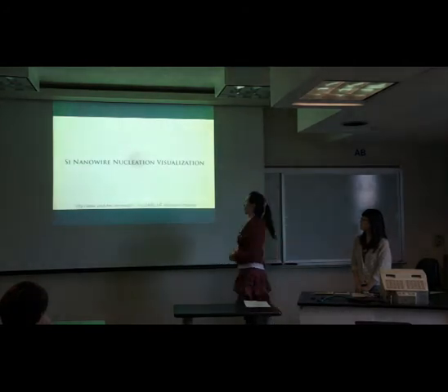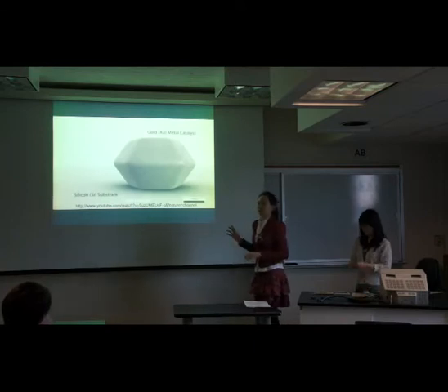To better understand the mechanism of this process, let me show you this video. We can see here a gold nanoparticle laid on the surface of the silicon substrate. This system is heated up to about 400 degrees C, and we pass silane gas as a precursor into this system.